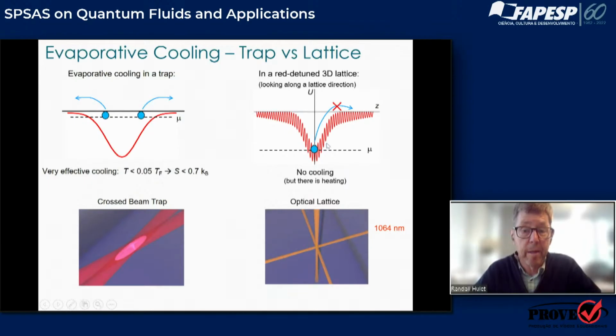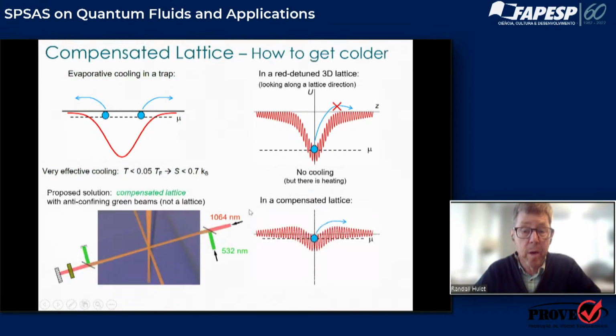And so that Gaussian width determines where this chemical potential has to be to get in the right density. So there's no evaporative cooling. We're very far from being able to evaporate. And so in an optical lattice, it's a very different situation than it is in a crossbeam trap. So we realized that there was a way around this.